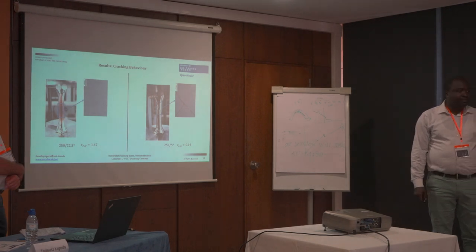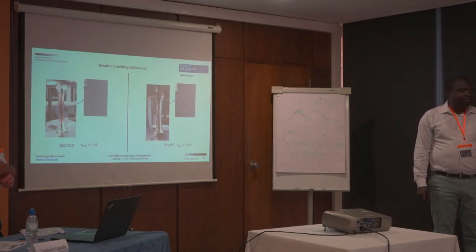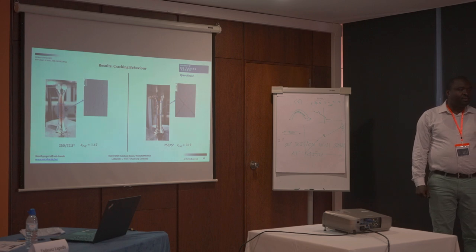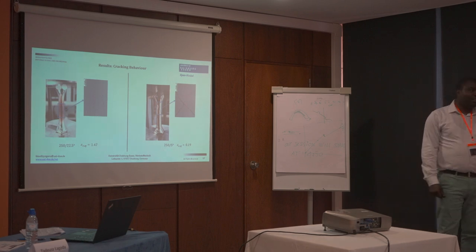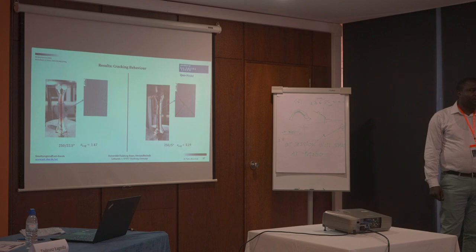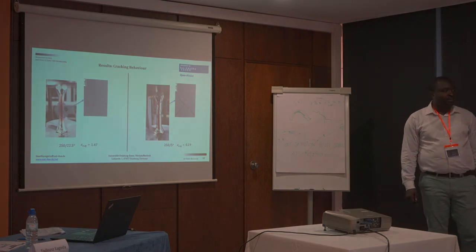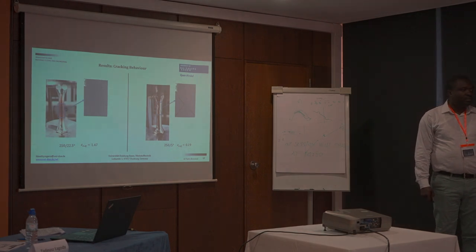You have no accurate explanation, or you have no clue why it's heating up? Because in fatigue loading, it's well known it should heat up, right? This is the dissipative mechanism. You're just pushing dislocations around one direction, the other direction, so it's just dissipating energy every time, and it can heat maybe 400 degrees. That is more than expected, but the heating up is not a problem. It's not actually related to the KAM map.